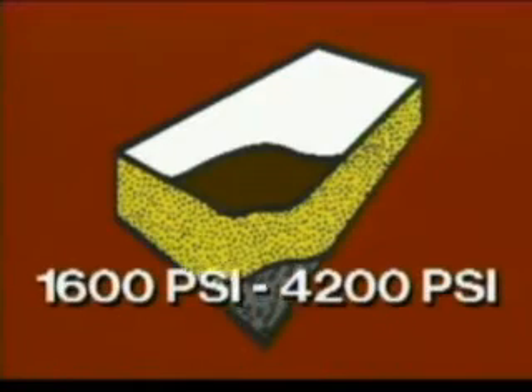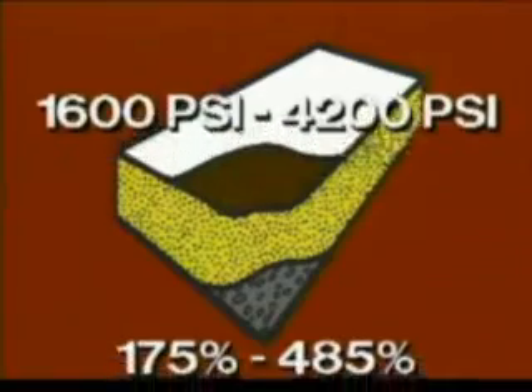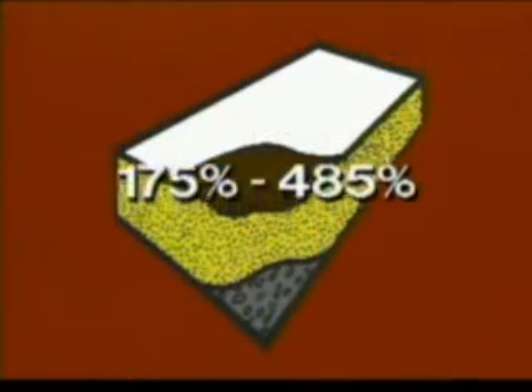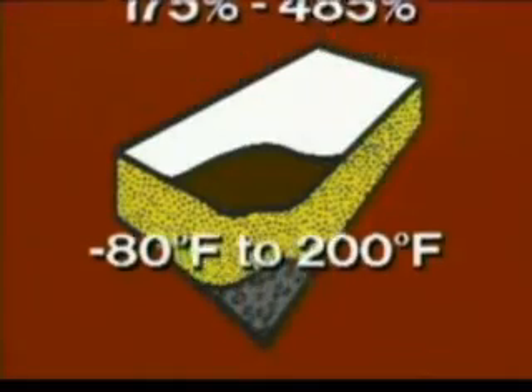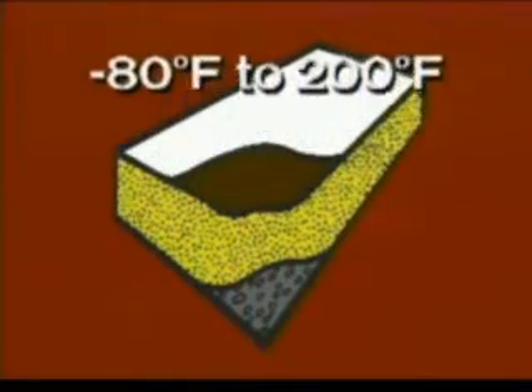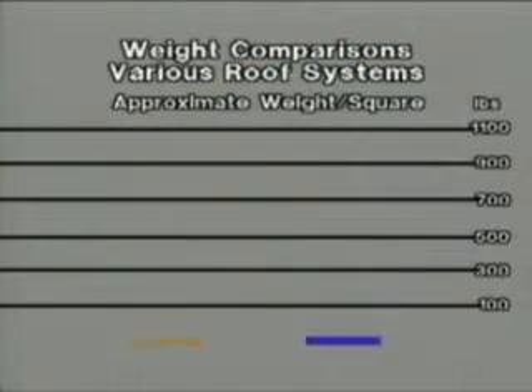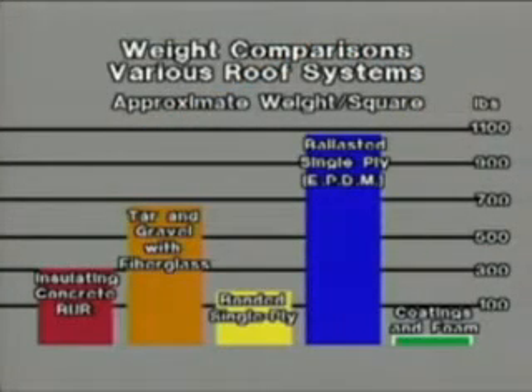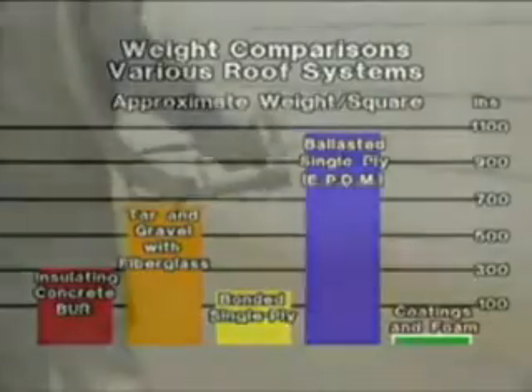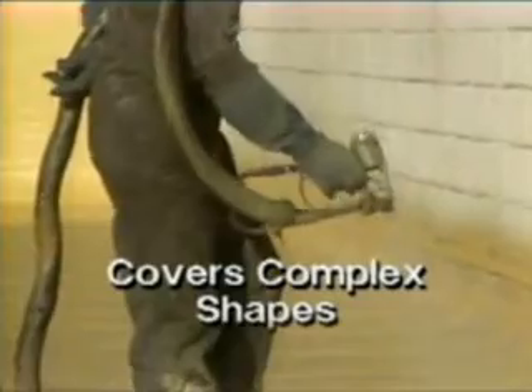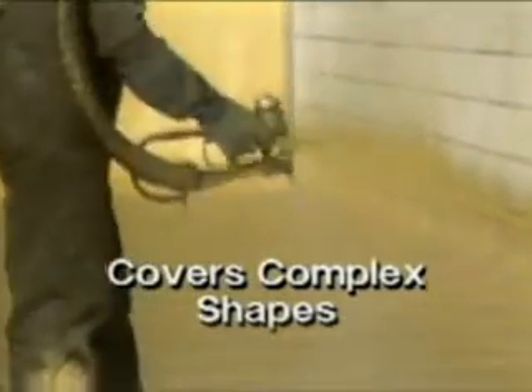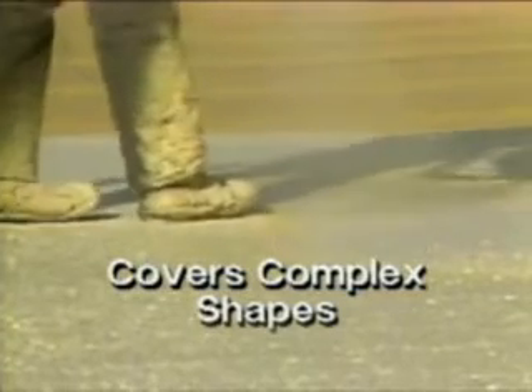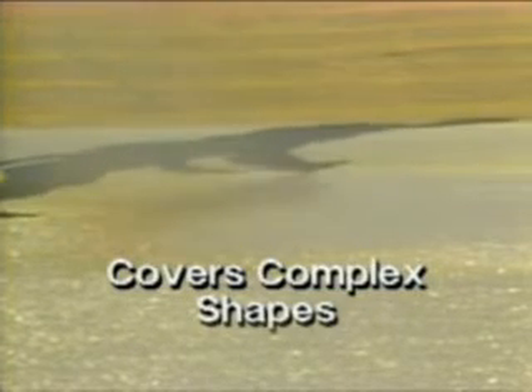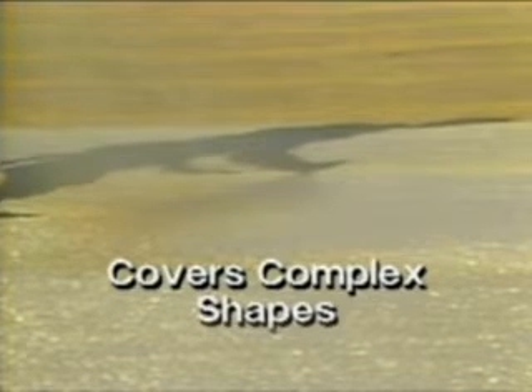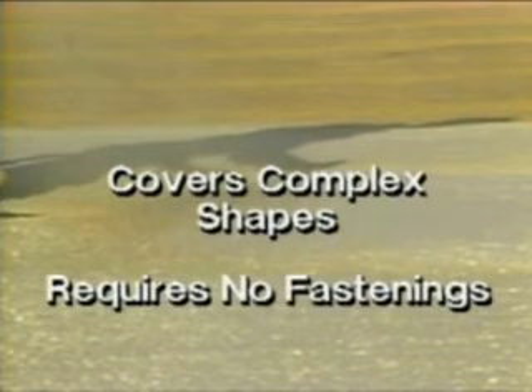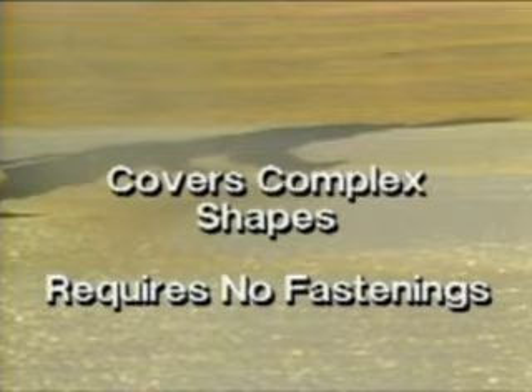They're tough, with tensile strengths from 1600 to 4200 psi, elongation factors from 175% to 485%, and service temperatures from -80 to 200 degrees Fahrenheit. A seamless, jointless, layerless, monolithic membrane can cut up to 90% off the weight of your roof. Cover flat roofs, complex geometrical shapes, protrusions, materials like glass, concrete, metal, built-up roofing composites, and solve a myriad of other problems. The elastomeric coating and foam roofing approach requires no mechanical fastenings, flashing, counter-flashing, glue, or penetration of the roof structure.